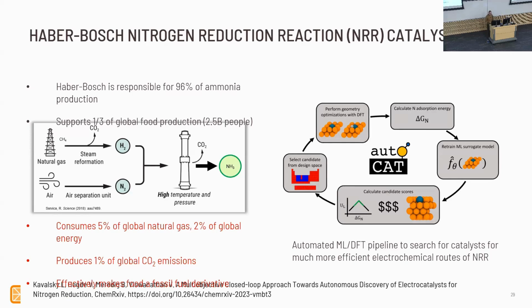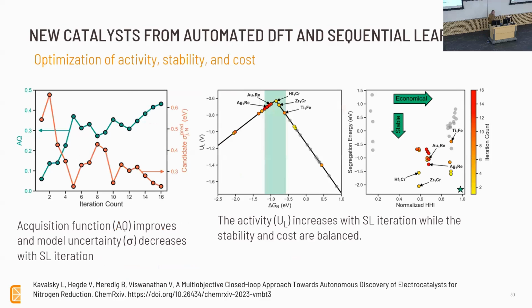And we worked with Carnegie Mellon on developing automated DFT pipelines accelerated with machine learning to be able to search for better catalysts for this nitrogen reduction reaction. So again, very similar to plots to what I showed before, but iteration count on the left and two different metrics for performance on this left plot. The first is AQ, which is the acquisition function, which takes into account the properties on the right, which I'll get to in a minute. And then the candidate predicted model uncertainty on the right.